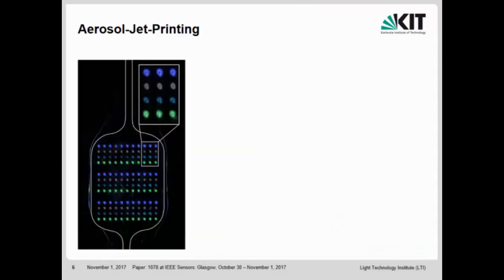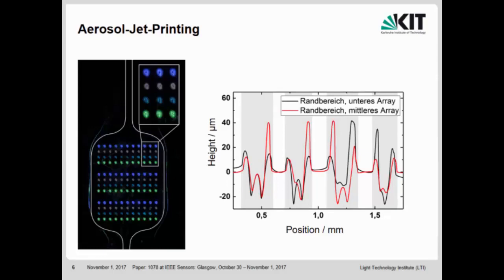In our case, then we functionalized the microfluidic channel. In this case, you see the fluorescence image of this, and so therefore the walls of the fluidic channel are not visible. With the aerosol jet technique, and by measuring a cross-section of this, you'll see that unfortunately we have the problem that we slightly dissolved the polystyrene from the bath. So this would be the top surface of the polystyrene, and within these spots you see that it's dissolved.